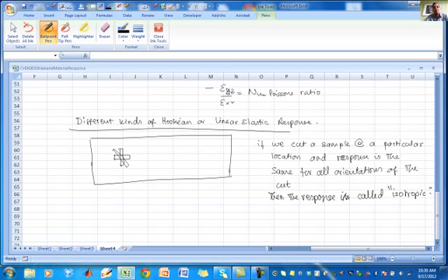But on the other hand, let us say I have a very, very accurate device which gives very high resolution, then maybe it doesn't turn out to be the same in all directions, because in the 10 to the minus 6th place there is a difference. So this is actually a function of how we measure and what we measure. This is really something to do with the model and not with reality.